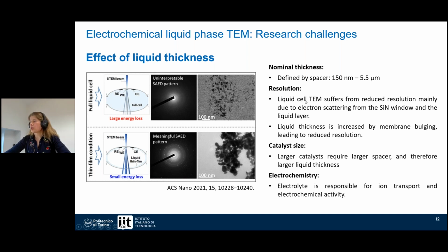We also need to take into consideration the catalyst size, because larger catalysts will require a larger spacer and therefore more liquid within the cell. Because obviously, if we have big particles and we place them on the working electrode, we need a spacer which is bigger than the catalyst, so as not to break the windows once we close the cell.